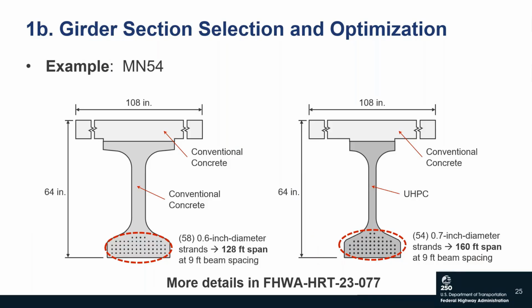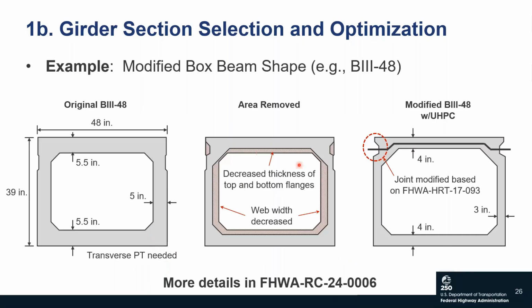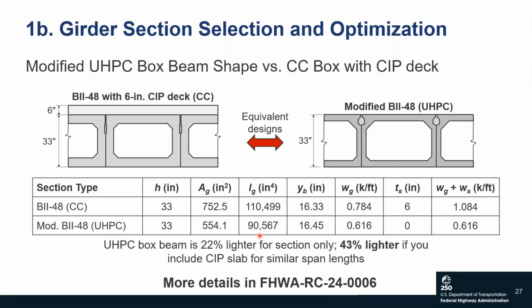Another example is shown here. So if we take a standard box beam section, if we increase the size of that foam blockout in the middle, we can decrease the web widths to 3 inches and the top and bottom flanges to 4 inches to reduce the weight of the section. On the left and right are equivalent designs. So the left, a 33-inch deep box in an adjacent box configuration with a composite 6-inch conventional concrete deck, is equivalent in terms of designs with a 33-inch deep UHPC box placed in that adjacent box configuration. So you can see, comparing these two, we're 6 inches shallower and 43% lighter using the UHPC section.